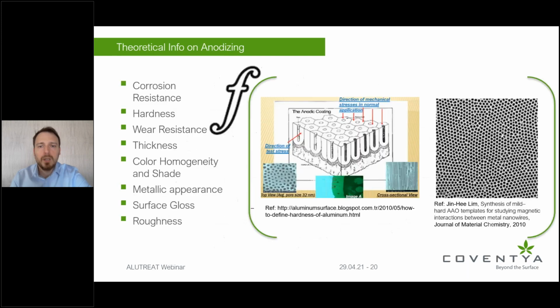Therefore, in order to get the properties that you desire, like corrosion resistance, hardness, wear resistance, and thickness, which are basically a function of the pore structure and how it is distributed or grown on the surface, one should very carefully control these parameters and adjust the surface as need be in order to have the right performance from this coating, so you might say.